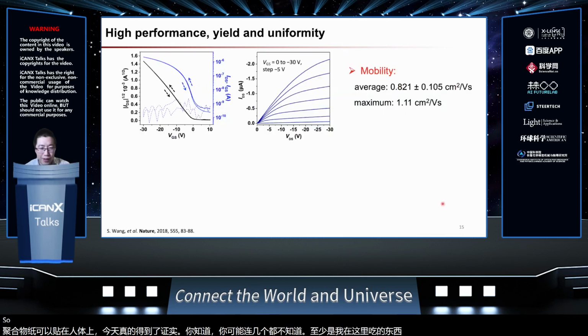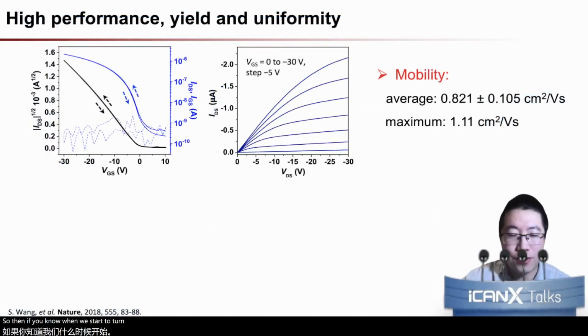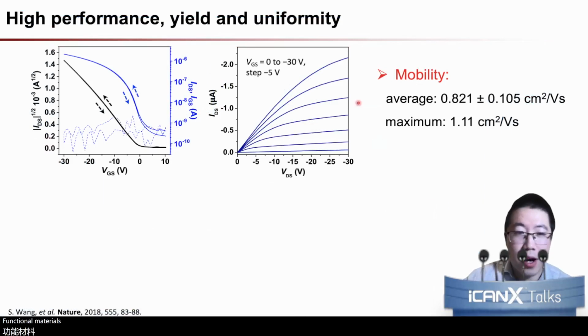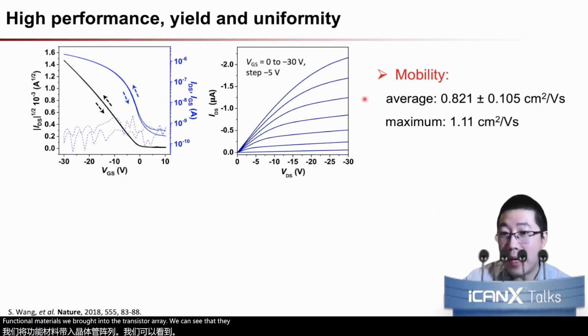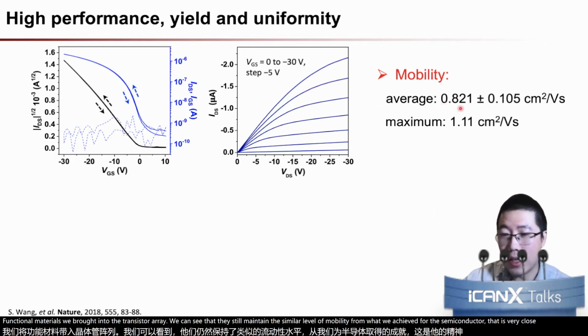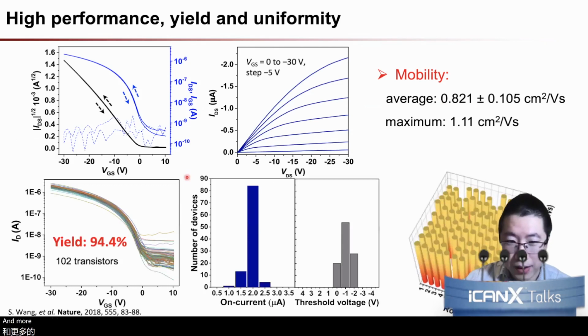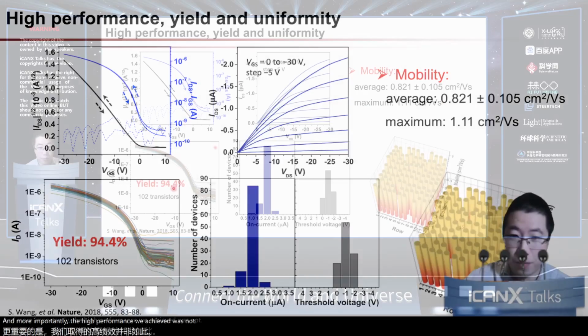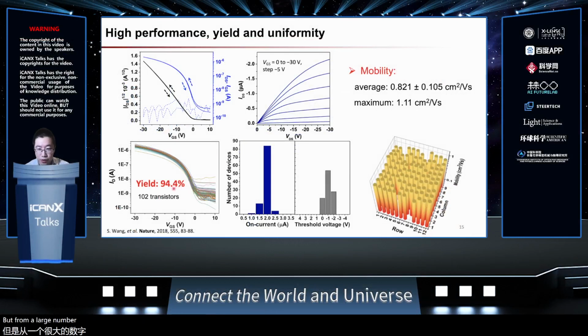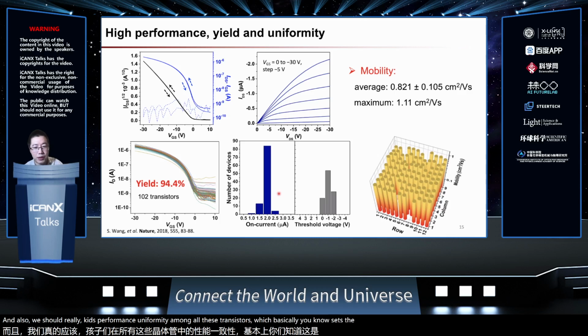So when we turn to the electrical performance given by the fabrication and the functional materials we brought into the transistor array, we can see that they still maintain a similar level of mobility to what we achieved for the semiconductor, very close to amorphous silicon. And more importantly, the high performance was not just from one transistor, but from a large number of transistors with a high yield, over 94% of the transistors in this array, and also with really good performance uniformity among all these transistors, which sets the most important performance requirements for further circuit development.